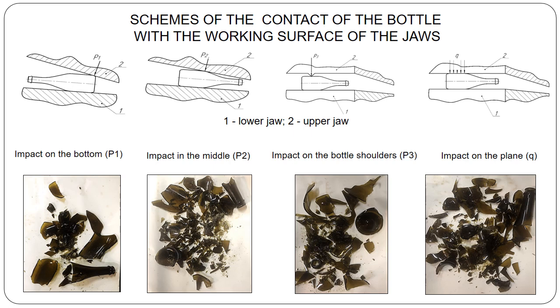The drop height is 0.7 meters. When a bottle is fed into the crushing chamber with the bottom towards the discharge window, the bottle is destroyed by a single blow. However, more than 50% of the glass breakage has convex shapes, which reduce the fill factor of the transport container.